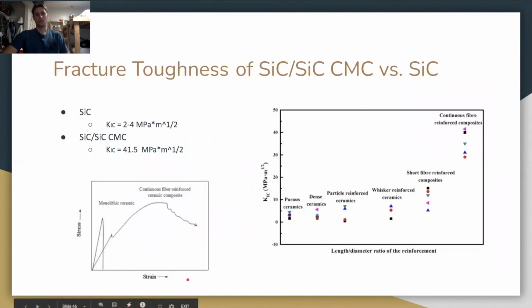We saw earlier that the fracture toughness K1C of monolithic silicon carbide is 2 to 4 megapascal square root meters. The fracture toughness of SiC CMC is 41.5, which is roughly 10 times greater. This is why we will be seeing SiC CMCs in future jet engines, since they are relatively resistant to fracture in addition to being able to withstand high temperatures.